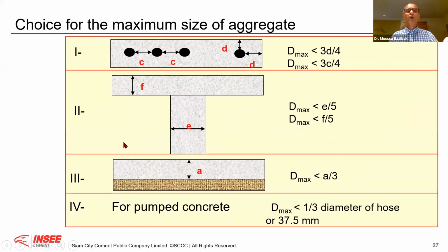Okay. Therefore, also you have, depending on your reinforcement, distance from the reinforcement to the edge of the mold, distance between two reinforcements, the size of the concrete, if it is on grade, if you have to pump the concrete. These are all information that you need to consider for the maximum size of aggregate. For example, in a slab, if my slab thickness is A, the maximum diameter should be 1/3 of the thickness, maximum. I cannot go above that. Or if I'm pumping a concrete, it should not be more than 1/3 of the diameter of the hose. And never more than 37.5 millimeter. Anyway, nobody will pump that. In Switzerland, we can pump even a 32 millimeter aggregate. Okay? Therefore, this is the third element that we need to consider.